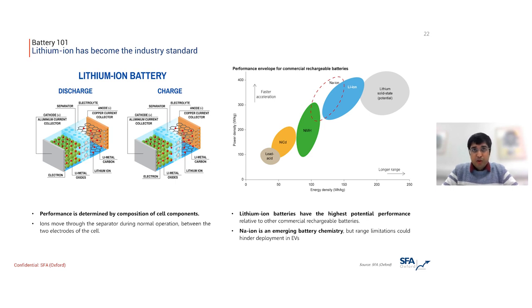In the last 12 to 18 months, there have been commercialisation developments for sodium-ion cells, but our view is that the performance of sodium-ion cells, especially in the first generation, is towards the lower end and they're not apt for the EV application. Rather, where they are suited is in alternatives which are less demanding on energy density or power density requirements.